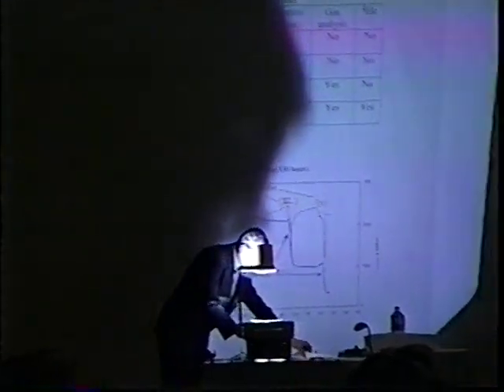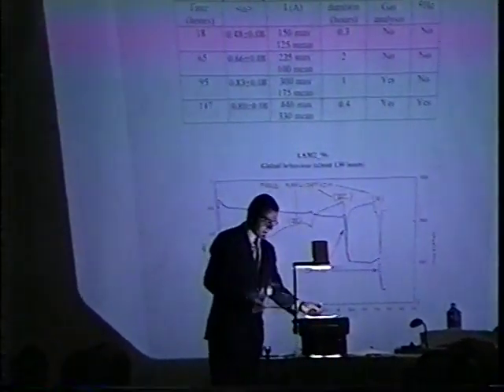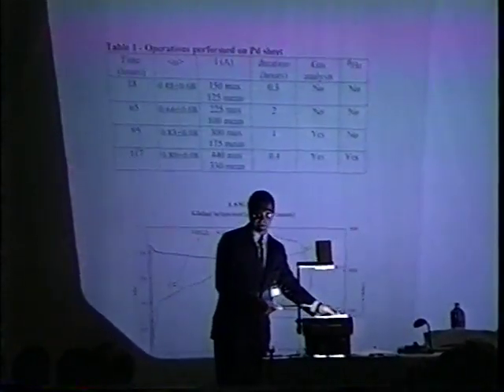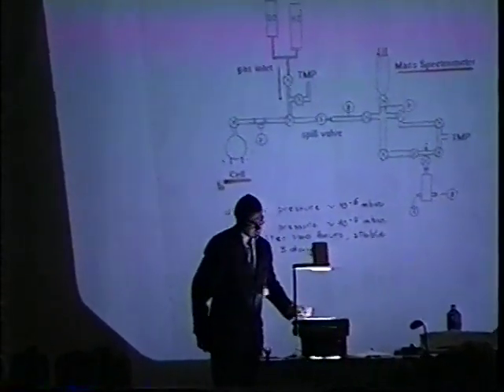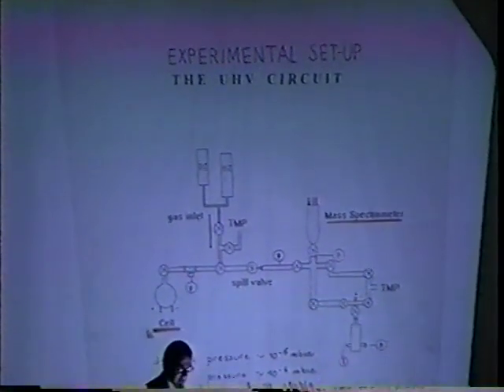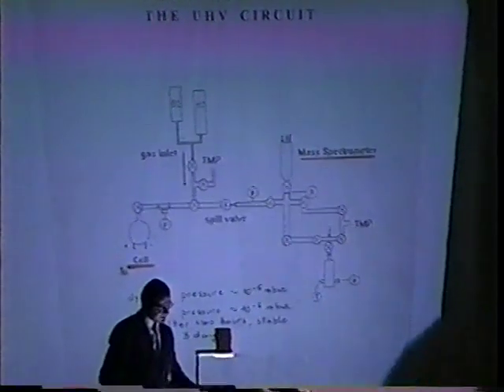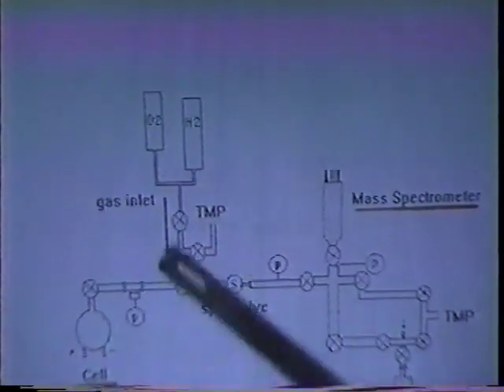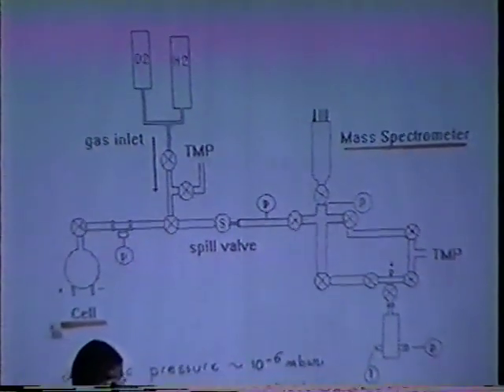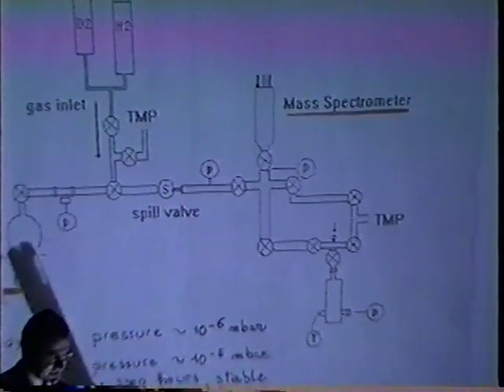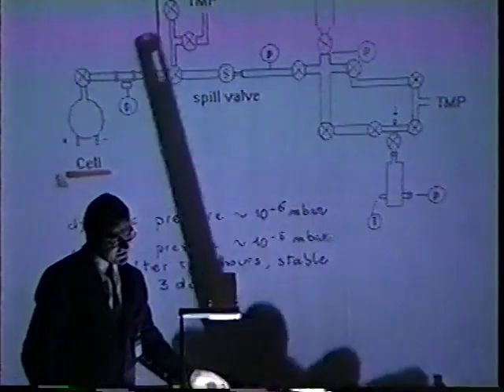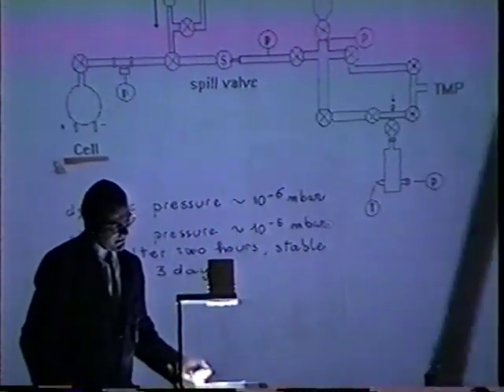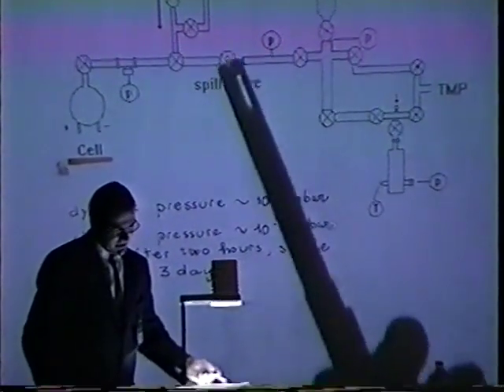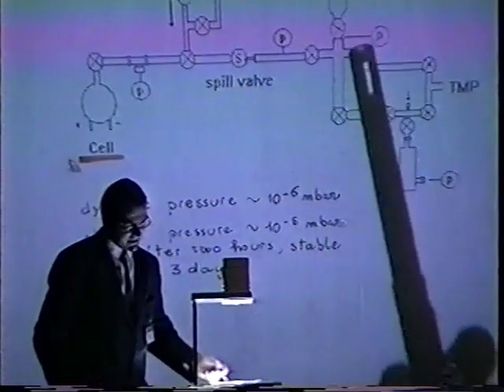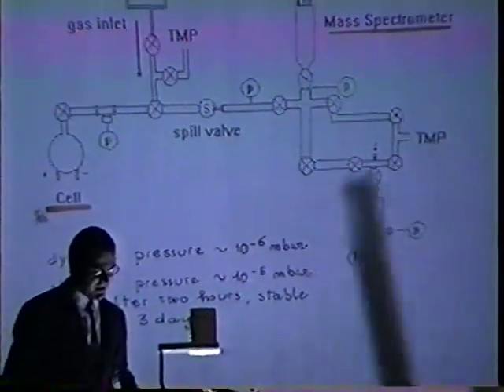It's perhaps important to briefly take a look again at the experimental apparatus, because first of all we have to talk about the blank measurements. So via the deuterium bottle, a controlled amount of gas can be put in this circuit, and after the opening of this valve, this amount of gas, in this case 2.7 bars, is admitted in the cell. Of course, the cell is immediately closed in order to work. The rest of the gas stays in this part of the circuit. This way it can be spilled to the spectrometer part where a static measurement is performed. Static, I mean without any action of pumps.